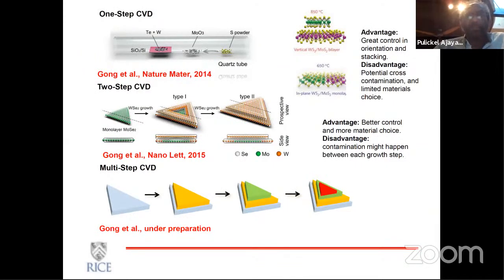And again, ultimately, if you want to build up these stacks, it would be quite challenging to do this by vapor phase deposition. Each layer is only a few angstroms thick. So if you want to get a reasonably thick film, you have to do this multiple times, or in a single growth step, you need to bring in multiple precursors and grow for long periods of time. So the growth itself is kind of challenging. And as I said, it's mostly an optimization approach.